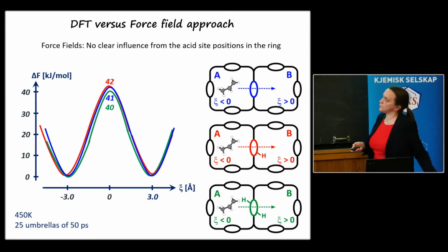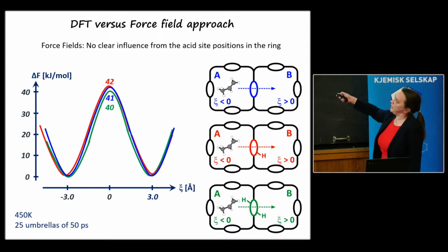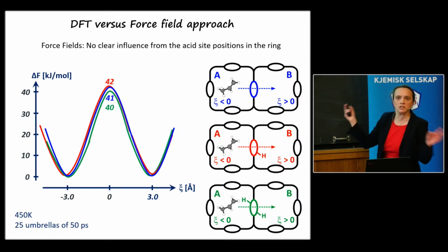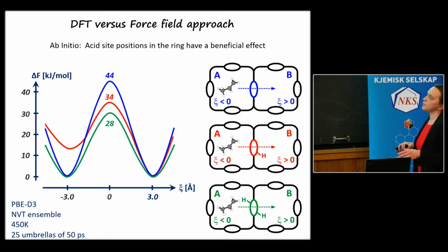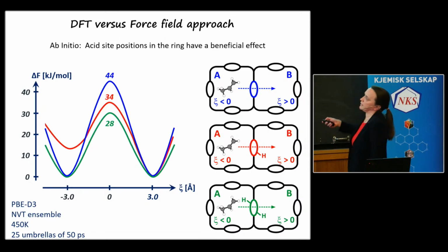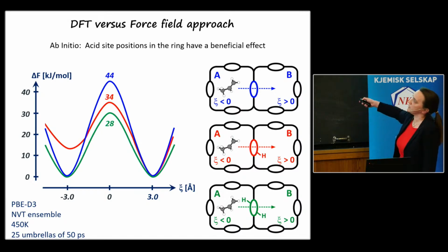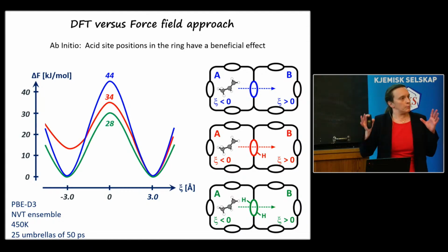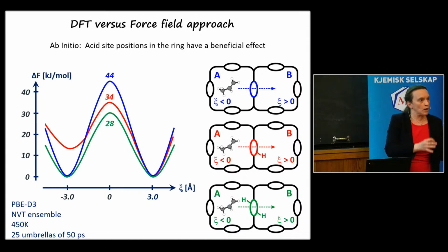So we started to do that with force fields. I will give more explanation tomorrow, but basically you can see here windows, no acid sites. Here there is one acid site. Here there are two acid sites. You see with classical force fields, everything's the same. Yeah? You see no influence of acid sites. Yeah? If you do it with quantum mechanical techniques, so DFT-based techniques, we can clearly see a difference. So for example, if here I have the red window, it's decorated with the Brønsted acidic proton, the barrier to go from one side to the other side is clearly decreased. If I have two Brønsted acidic protons, it is more decreased. So the acidity is clearly important to help the propene to go from one side to the other side.